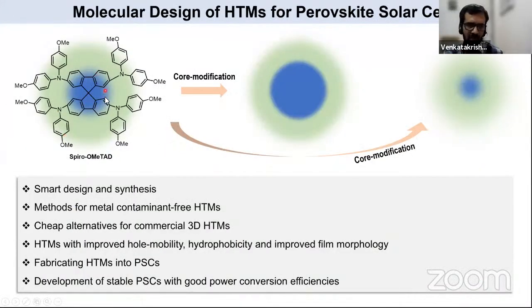So we thought of modulating the core and also the periphery. One can even expand the core, can also think of shrinking the core, but retaining the peripheral substituents more or less the same, or you can also tweak the diaryl amino units and vary its characteristics and look in detail at their performance in perovskite solar cells. By expanding the core, you are bringing in larger pi conjugated systems, but by shrinking them, you are minimizing the pi conjugation, but retaining the spiro. So spiro is good for morphology, but the pi conjugated system is good for transportation. If you are able to do that, we are looking at efficient devices at the end.